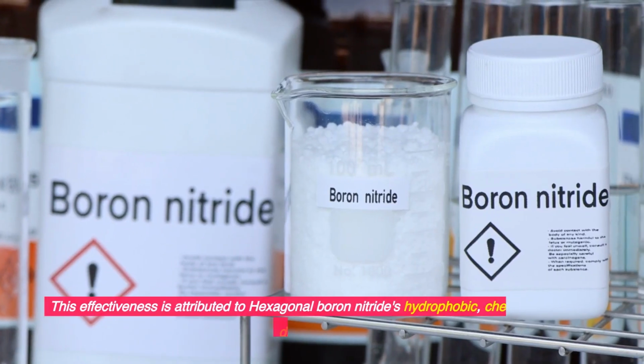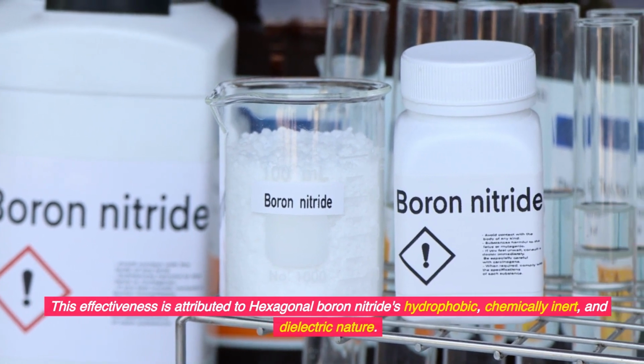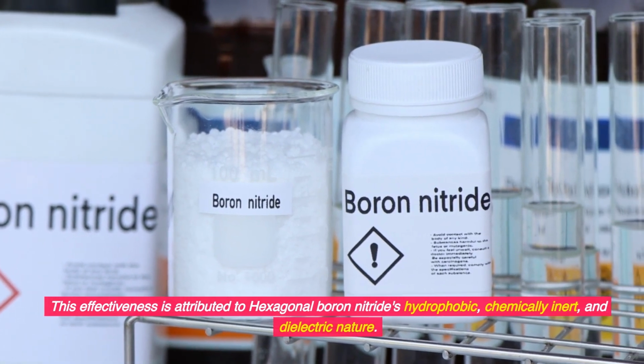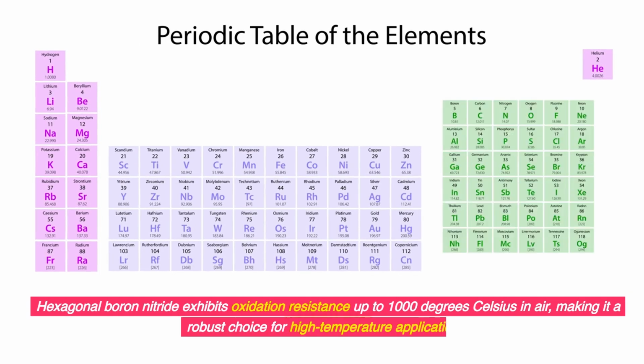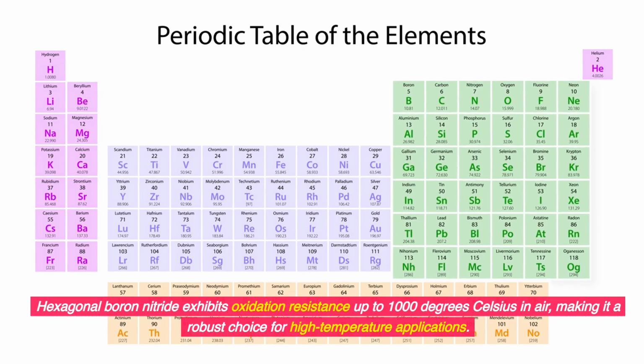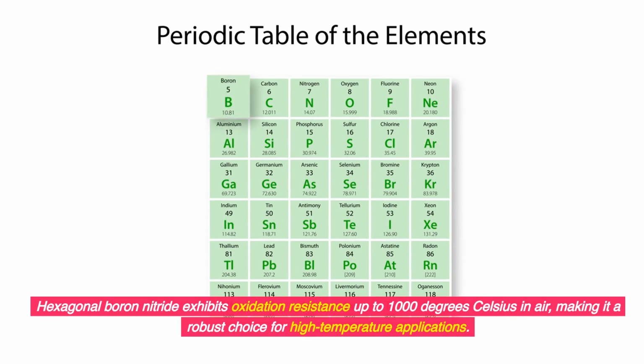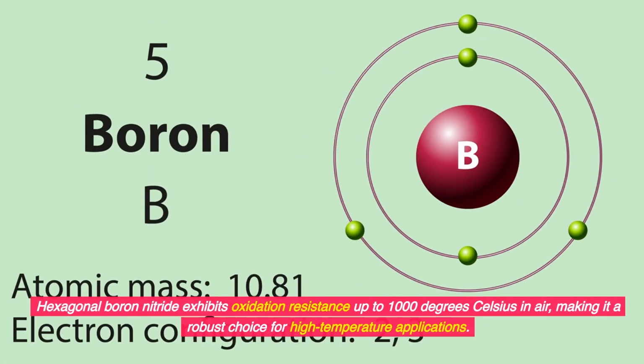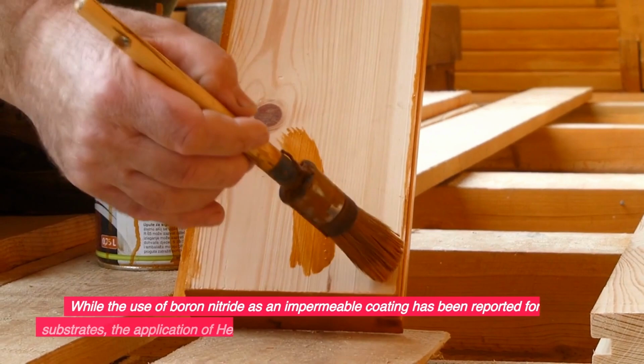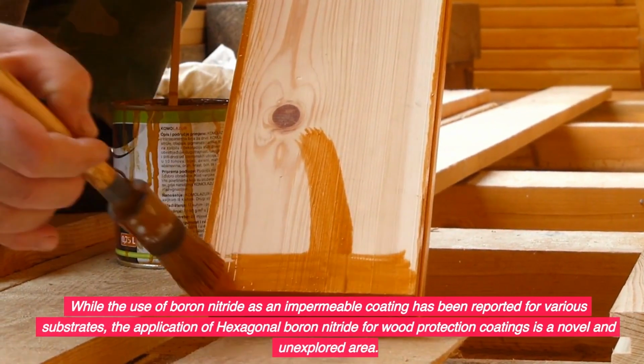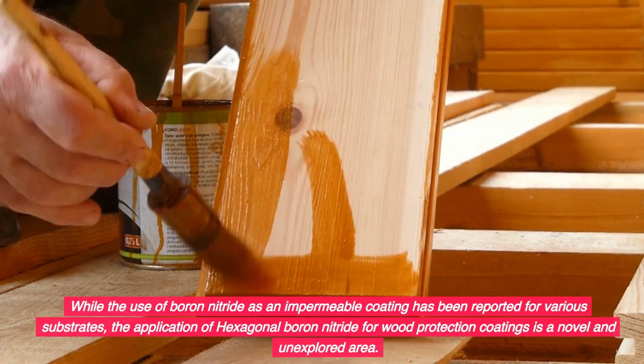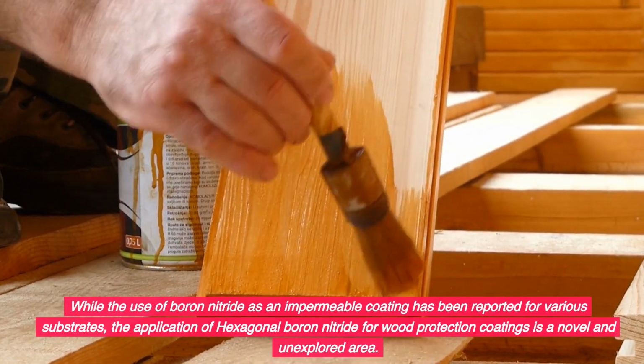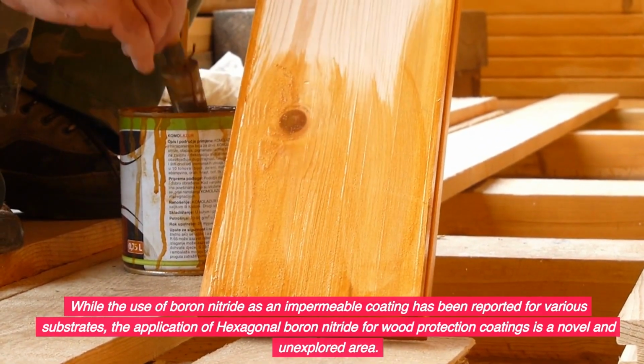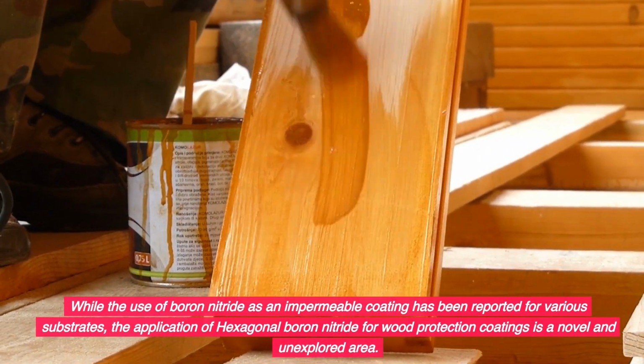This effectiveness is attributed to hexagonal boron nitride's hydrophobic, chemically inert, and dielectric nature. Hexagonal boron nitride exhibits oxidation resistance up to 1,000 degrees Celsius in air, making it a robust choice for high-temperature applications. While the use of boron nitride as an impermeable coating has been reported for various substrates, the application of hexagonal boron nitride for wood protection coatings is a novel and unexplored area.